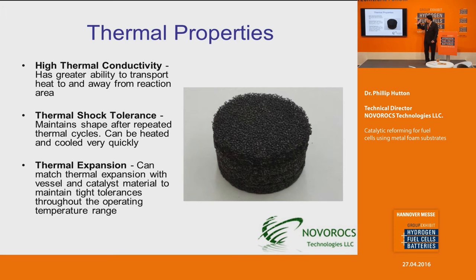Thermal shock tolerance. This is another characteristic of foam that is advantageous compared to ceramics. With the metallic foam, you could heat up the foam or cool it down almost as fast as you want to. A lot of catalysts require you to heat up or cool down the catalyst over a period of time to prevent the catalyst from cracking. With the metal foam, you have very high shock tolerance, and it maintains its shape after repeated thermal cycles.